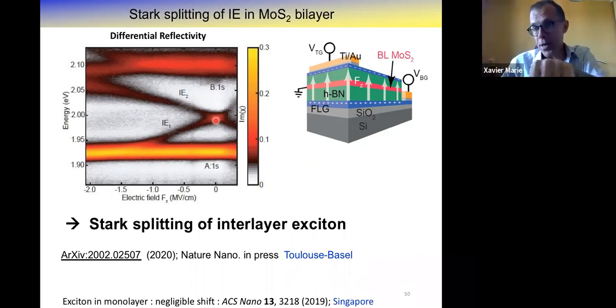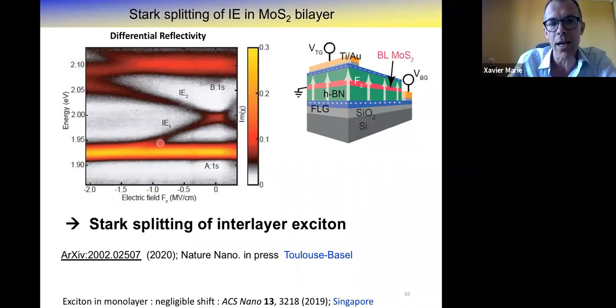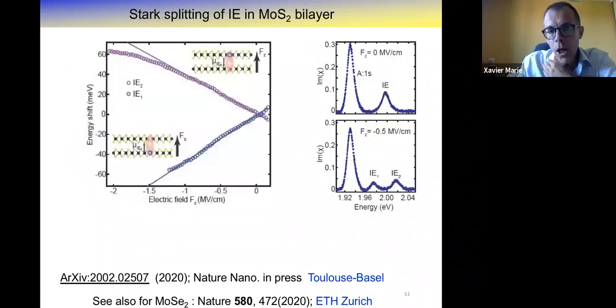So if we apply an electric field, it will shift in opposite direction. And indeed, we lift the degeneracy, interlayer exciton 1 will go down, interlayer exciton 2 will go up. And so we observe this Stark splitting. We can just get the energy position as a function of the field and quantify the Stark shift.